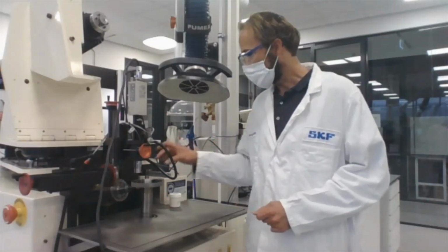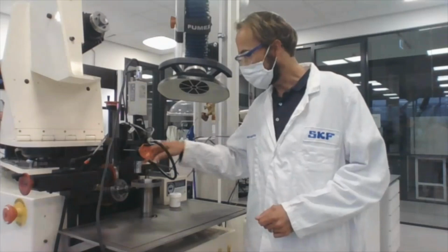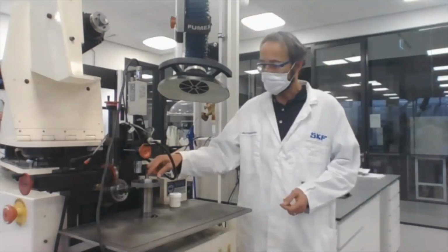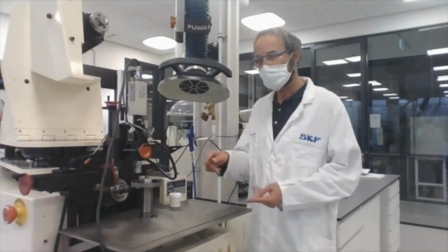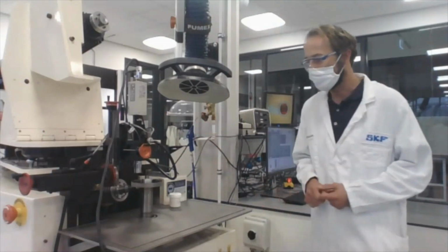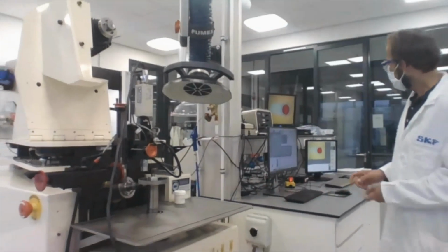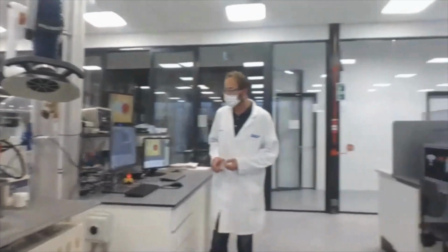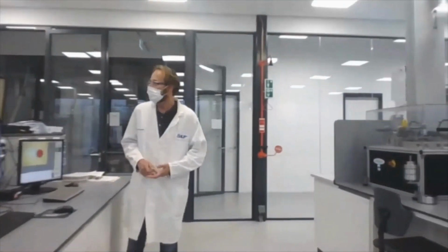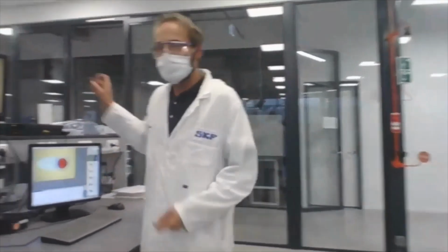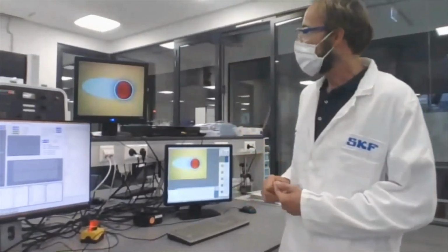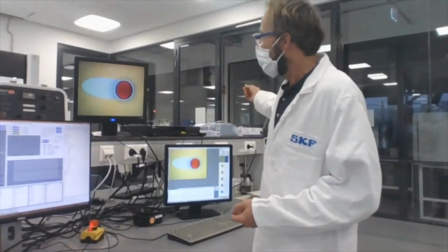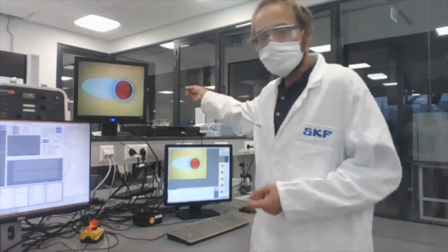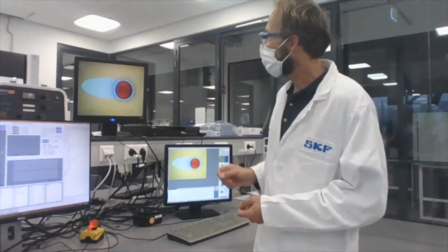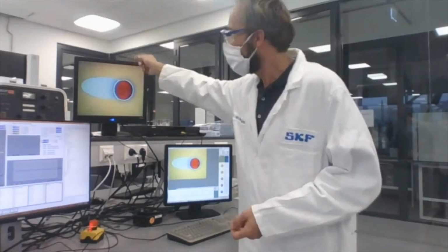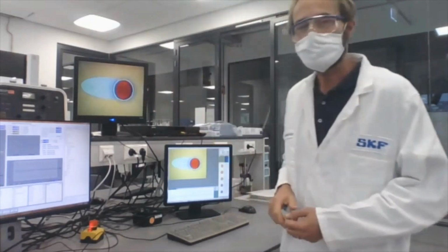Currently, we are testing an oil. The ball is positioned underneath the disc. That is lubricated with a few droplets of oil, and that is sufficient to build a film. When we then look at the image from the microscope, you can see that the oil is contaminated with drops of water, and the droplets are coming towards the contact, but in fact they do not go through the contact, but they move around the contact, and then they gather in the outlet region.